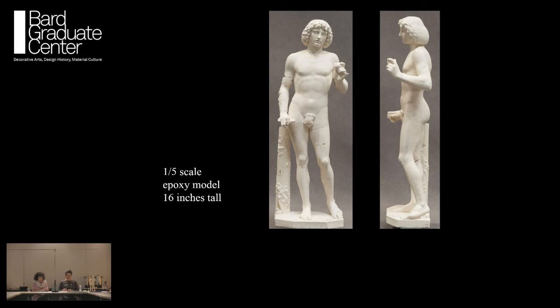And it really helps to illustrate some of the issues that would influence the way we started to think about reconstructing Adam. So if you take a look at the image, first you'll notice that there are twice as many breaks on the left leg as there are on the right. The high quality of the Carrara marble resulted in very clean breaks that fit together tightly. Therefore, we knew that displacement of the fragments from any added adhesive would become one of our primary concerns. While many of the breaks are in compression, that is straight across or parallel to the floor, there are a few critical joints that experience a combination of compressive, tensile, and shear or slipping stress.